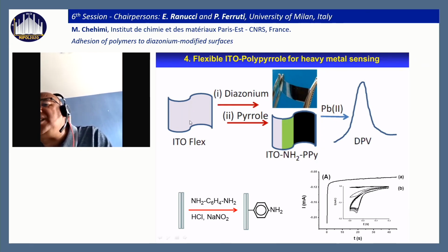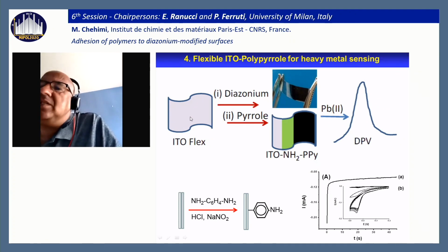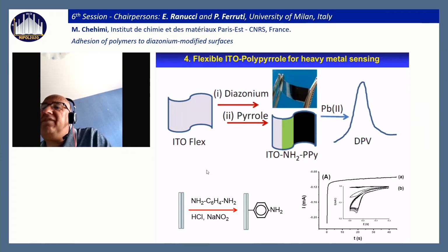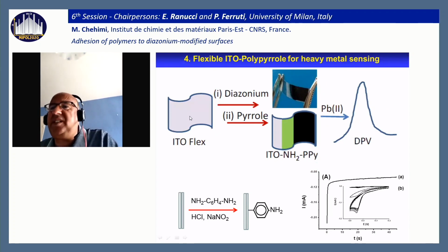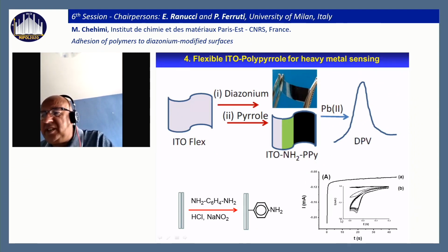We worked on flexible ITO, indium tin oxide, electrodes. They are coated on PEN foils, maybe 200, 300 nanometers of ITO coated on the substrate. They are sold as A4 sheets. You can cut to the size you want. We have worked on diazonium modification and the electropolymerization of pyrrole. You can see here by electrochemistry that when we graft the diazonium salt of this phenyl diamine molecule, after several cycles there's a passivation of the ITO.